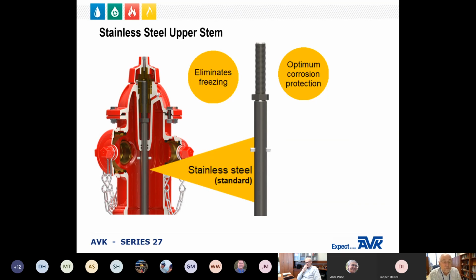We found that under certain conditions, water could creep underneath the old style thin brass sleeve and freeze. The expanding of the freezing water would split and crack the thin brass sleeve, allowing water to enter the lube chamber and destroy the lubricant within. We all know that when the lubricant is destroyed, the hydrants become very difficult or even impossible to operate.